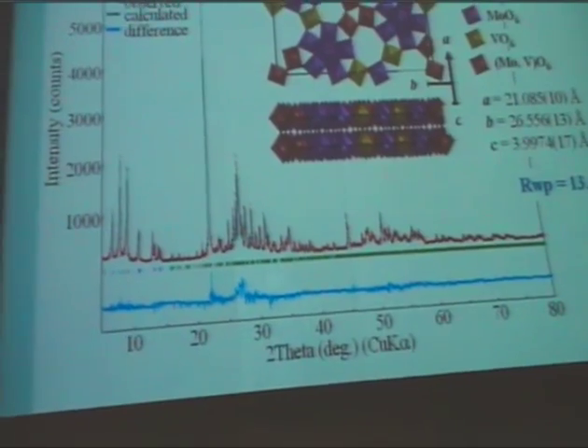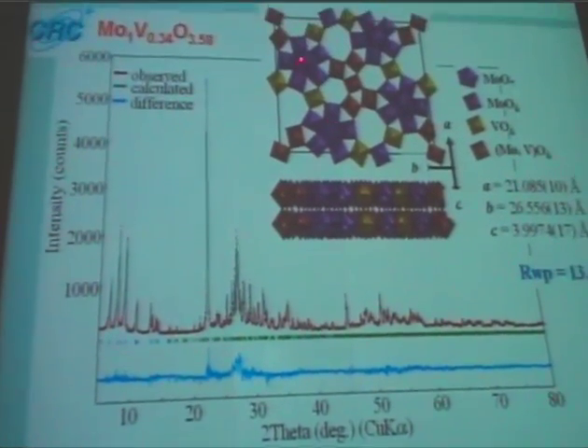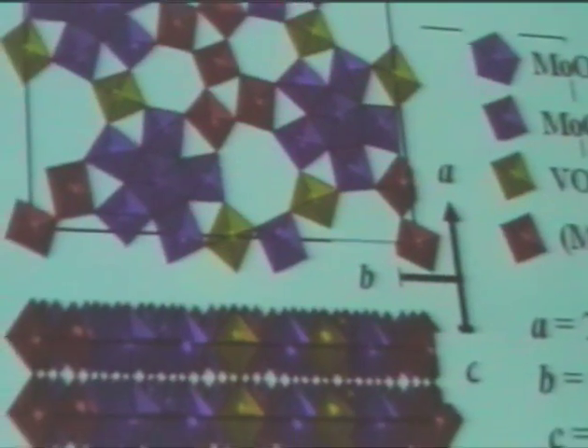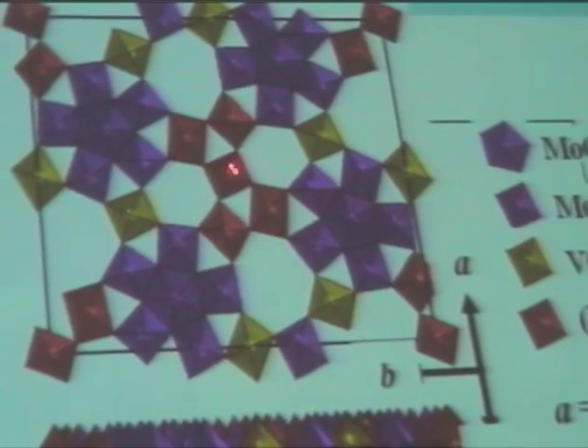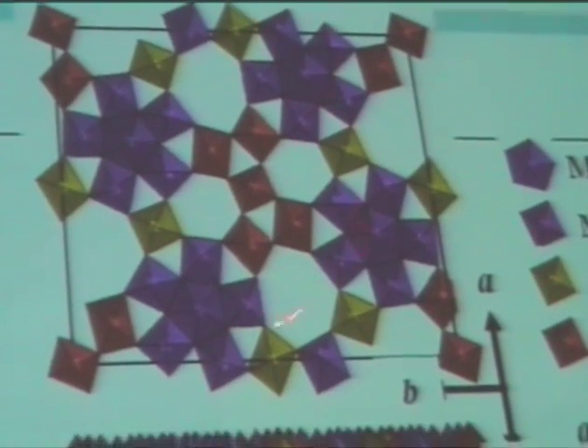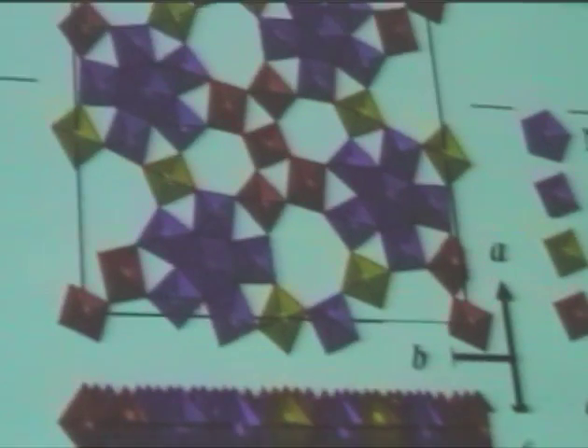We proposed the structure model here. It shows in a little detail: here in the pentagon, all the corner atoms are molybdenum outside, and there is a pentagonal bipyramidal unit surrounded by octahedral molybdenum. These units are connected together with edge-sharing octahedra going around, and we have a vacancy here, but this vacancy has been occupied by molybdenum or vanadium. We proposed this structure, and based on this structural model we conducted a Rietveld analysis, and we got reasonable results.